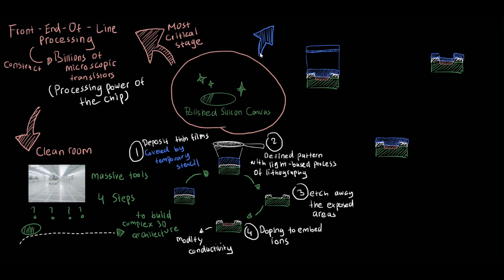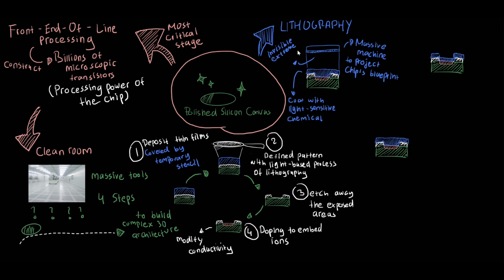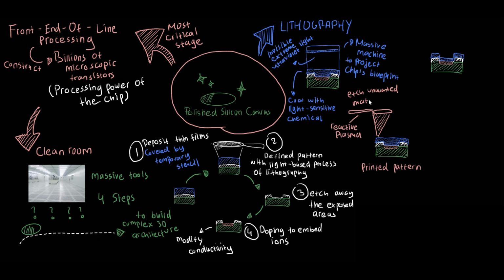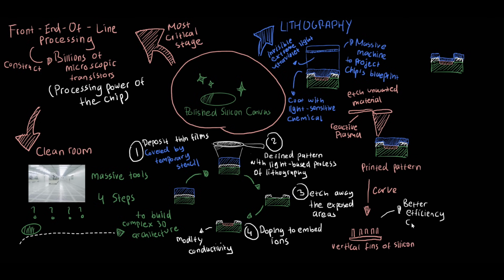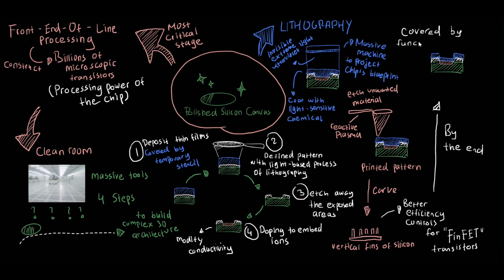The most technologically demanding of these steps is lithography, where we coat the wafer in a light-sensitive chemical and use a massive machine to project the chip's blueprints onto the silicon using invisible extreme ultraviolet light. Once this specific pattern is printed, we use reactive plasma to chemically etch away the unwanted material, carving out tall vertical fins of silicon that allow these modern FinFET transistors to control the flow of electricity with far greater efficiency than the flat designs of the past. By the end of this stage, the wafer is covered in a dense forest of functioning switches, but they are still isolated islands that are waiting to be wired together.